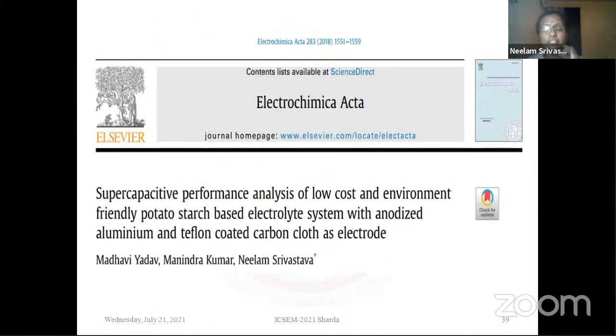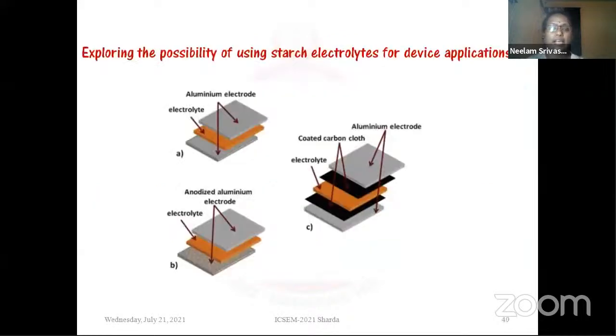And recently, since the electrolyte material was showing very good properties, we tried to test our system with well-known available electrode materials, which are very common, and on which a large number of studies have already been carried out. These two were the anodized aluminum and Teflon-coated carbon cloth, which are available commercially. So we started our studies with this, and we have used this kind of stacking structure for the fabrication of the cell. So this is how we have used it.